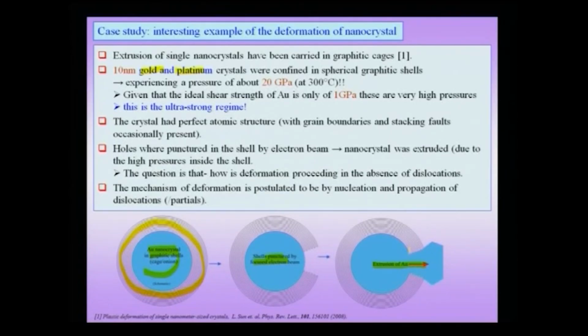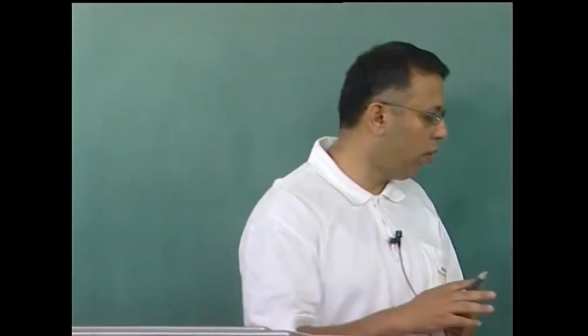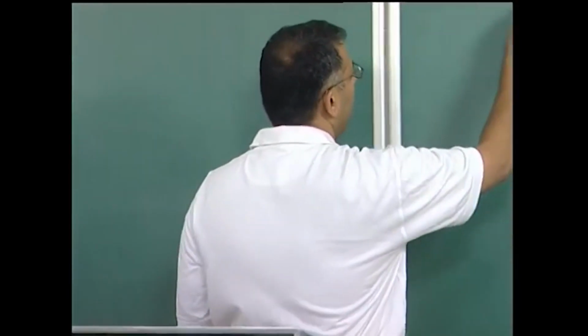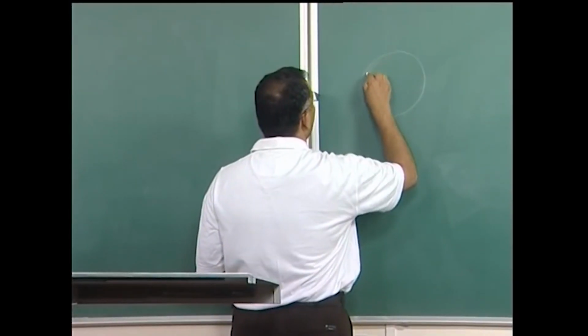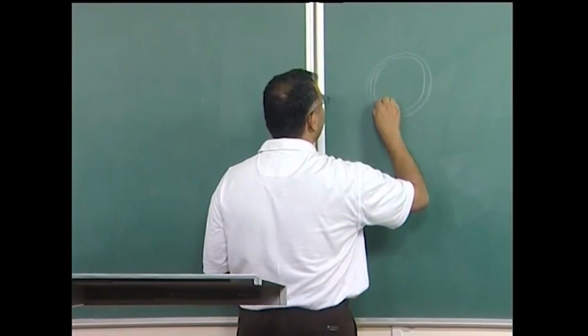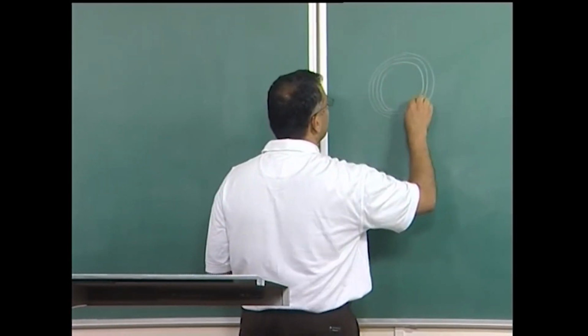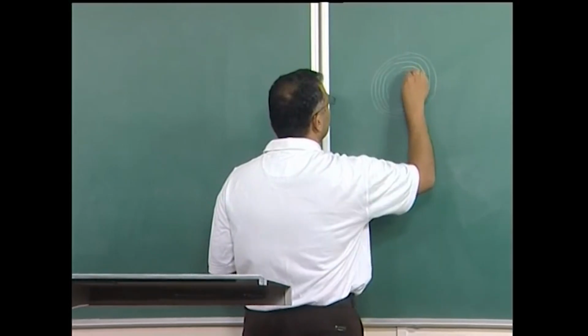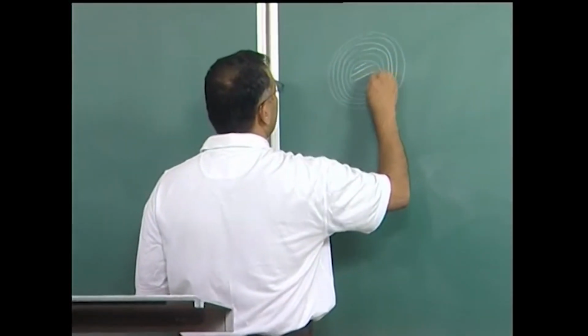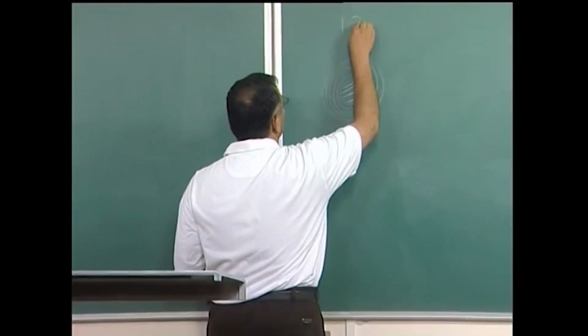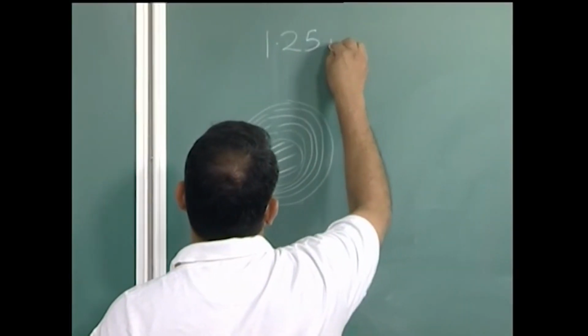Now, if you go back to a very early experiment, going back to Ajayan, what he did was he took such a carbon onion shell, and without of course the gold inside, he put it under the electron beam of a 1.25 million volt electron microscope, and to his surprise he found that the core region of this carbon onion... So, you have these nice carbon onion shells. So, this is a schematic. We found that the core region purely under the electron irradiation. So, he was using an electron microscope with 1.25 million volt.